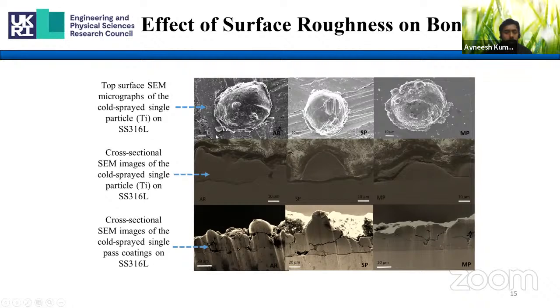So AR stands for as received substrate. As received means the average roughness value is around 5 micron, for semi polished it was around 0.5 micron, and for mirror polished surface it was around 0.03 micron. Then we impacted titanium particles, looking at the single particle interaction from the top surface.